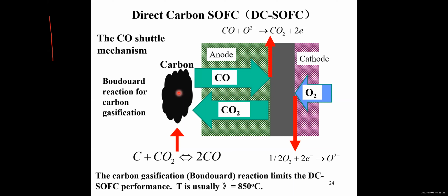Actually, the carbon is utilized in an indirect way. The carbon is first gasified by carbon dioxide to produce carbon monoxide, CO. Then this is gas, right? The gas can be easily diffused from the carbon fuel to the interface between the anode and the electrolyte. Then the CO can be oxidized to produce CO2 and electrons. And the CO2 can be diffused from the interface to the carbon to gasify carbon again. So this whole process will proceed continuously, and the carbon can be continuously utilized for power generation.